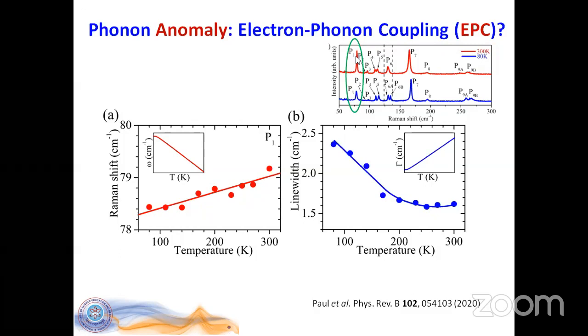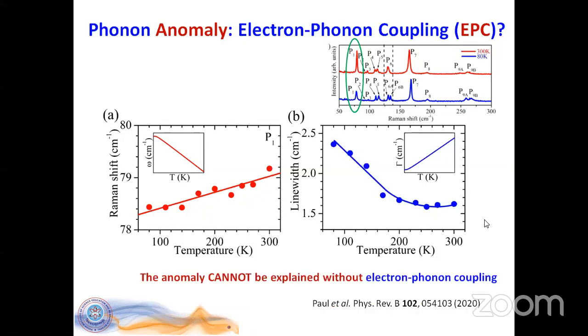But on the other hand, for this crazy mode, P1, it shows exactly the reversal behavior. You can see that with increasing temperature, the frequency shows an increasing trend, but the line width shows a decreasing trend. So that's very, very unusual, and this is what we are referring to as phonon anomaly. If you try, one by one, to look at the possible reasons for this anomaly in this system, the only thing that can explain it is the electron-phonon coupling. Without that, we cannot explain this anomaly in the phonon. So here we would like to emphasize that this anomaly in the phonon is because of the electron-phonon coupling in the system.